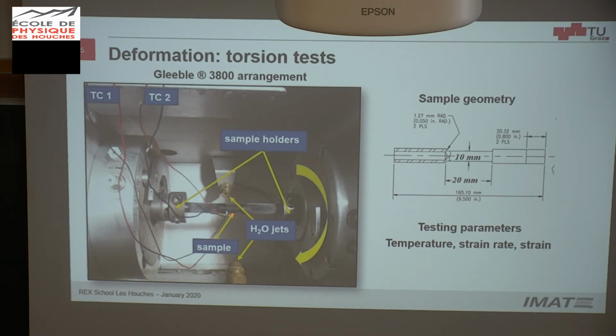So you put the thermocouple on the shoulder. The shoulder looks like this. The sample looks like this. It's hollowed at the heads. And with this, more or less, you get the same area here as here, so the same section, the same resistance, and with this, more or less the same temperature. What we usually do is put thermocouples here, do heat treatments and calibrate until we know which temperature we have to control here or to set here to get here what we want.